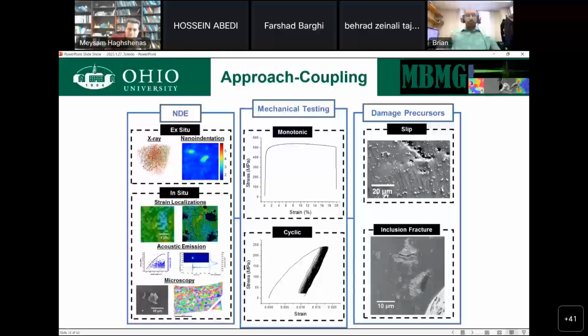And what do we get from this? If we combine the non-destructive testing, it could be ex situ methods like X-ray analysis or some of the nano indentations that we're trying to get some understanding of the material, or in situ like the DIC, which in the previous case I showed you at coupon scale. In this case, I'm showing you if you use DIC from SEM images, you can obtain information about the particles and how strain forms around them, or dislocations. And acoustic emission, microscopy, whatever you're measuring as you're collecting data, the loads, the data themselves, and then try to understand what are the damage precursors, as I call them now, that are going to lead to how this material ultimately fails. And we can do this at the microscale, and we can go up in scale, whatever scale you want from there.